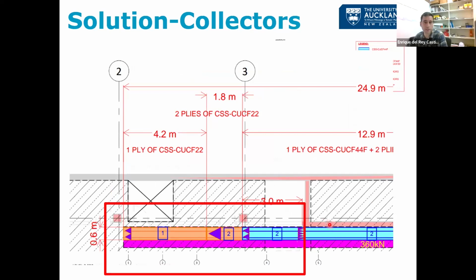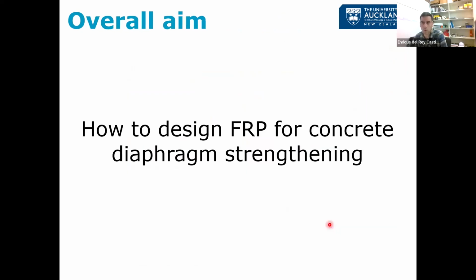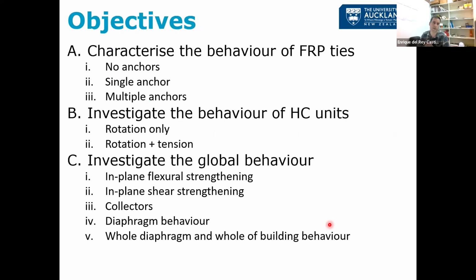The problem is this is being used for many years, but in reality, we don't know how to design FRP for this application. We are using equations that were developed for other applications like 3-point bending or 4-point bending beams, or that were developed using sizes that are not realistic, often only like 300 millimeters long, 1 millimeter thick, and these ties are meters long and 3, 5, 7 millimeters thick. So it's not realistic. And that's where we started about 3.5 years ago.